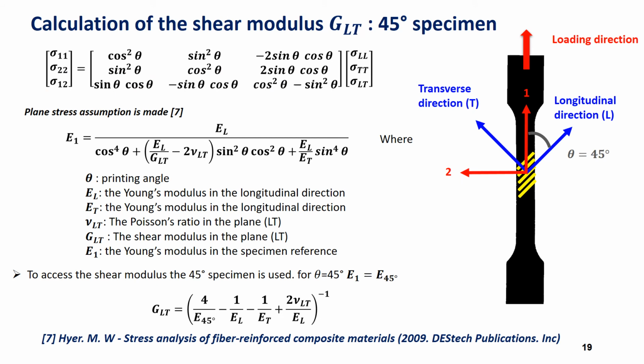The shear modulus is calculated using the stress analysis of fiber-reinforced composites. Using a coordinate transformation of stress from the global reference to the local one, we can calculate the shear modulus using both longitudinal and transversal Young modulus previously identified and the experimental value of the Young modulus of the 45-degree specimen.